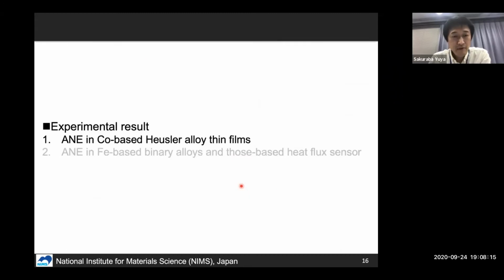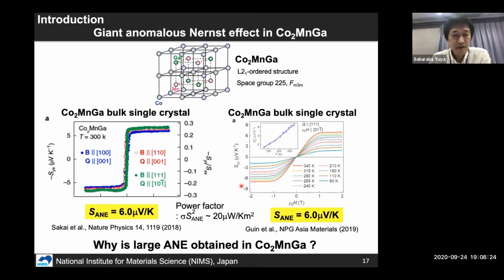So from now on, I'd like to show the experimental results in several materials. The first one is the anomalous Nernst effect in the cobalt-based Heusler alloy. As you may know, recently two research groups in Japan and Germany reported a very large anomalous Nernst effect, a thermopower of 6 microvolt per Kelvin, in the Co2MnGa full Heusler compound. Actually, this value is the highest anomalous Nernst thermopower ever reported.